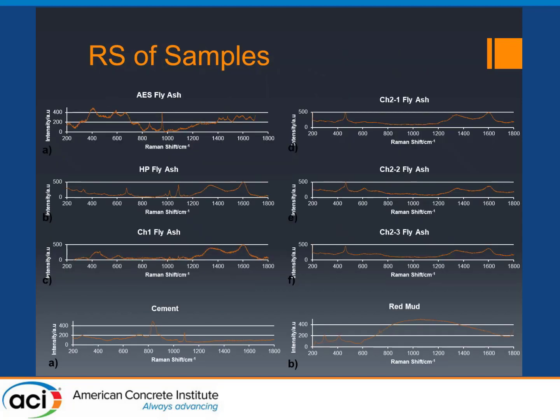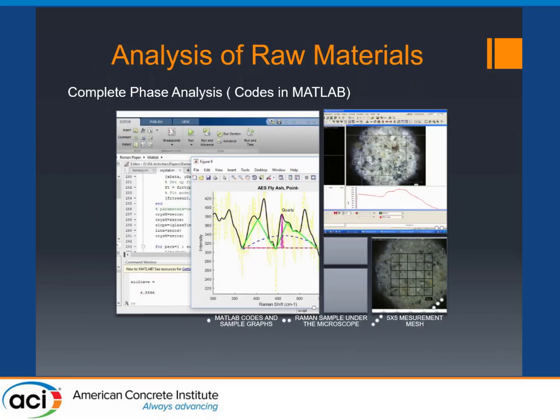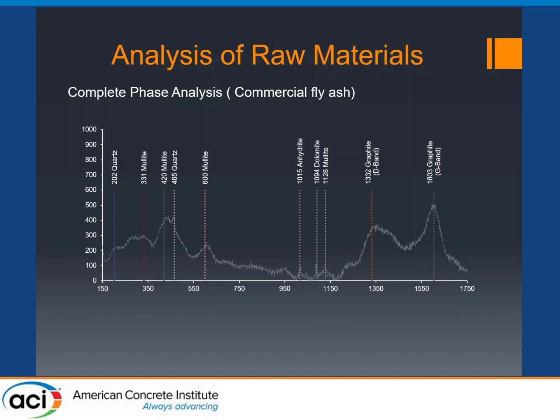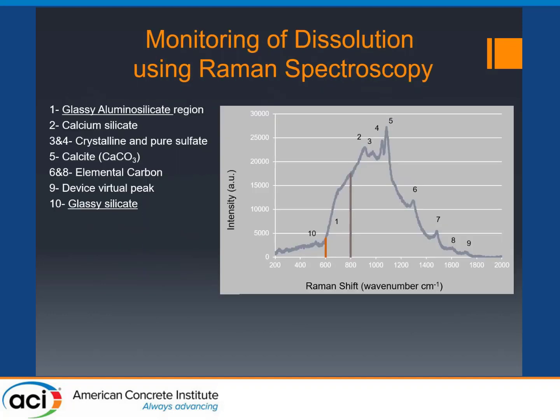All right, so this is some other Raman samples for different type of precursors, including fly ash and slag and Red Mud. We use MATLAB code to quickly detect and quantify both crystal peaks and also amorphous bandwidths. So we can better quantify precursors and also monitor the kinetic reaction. This is an example of fly ash.